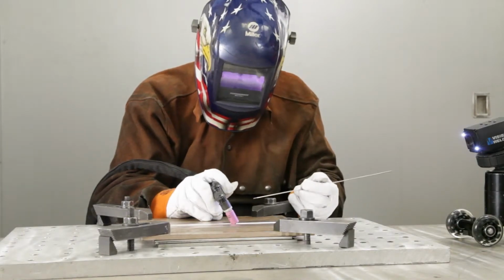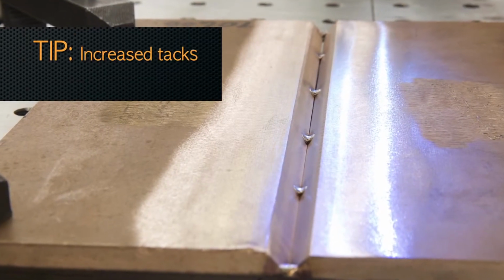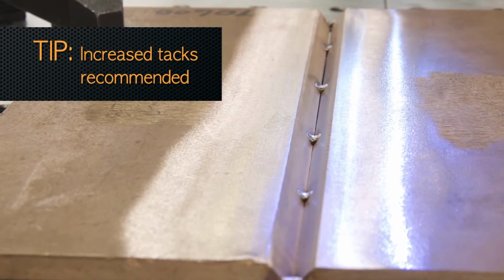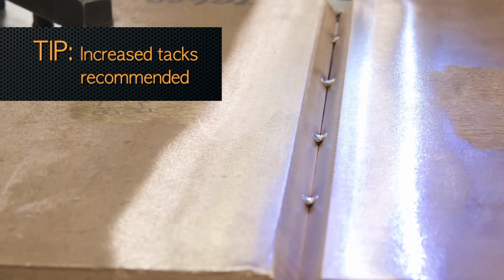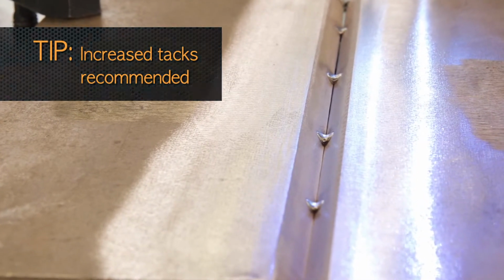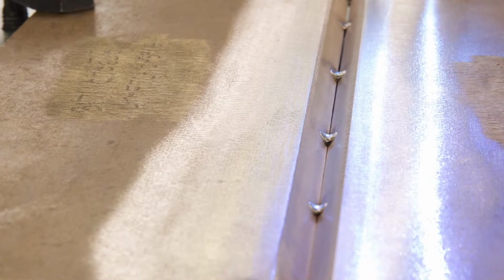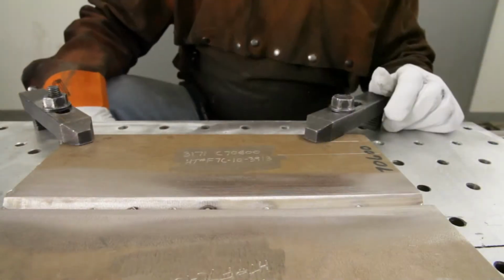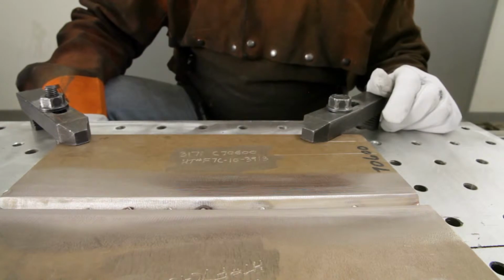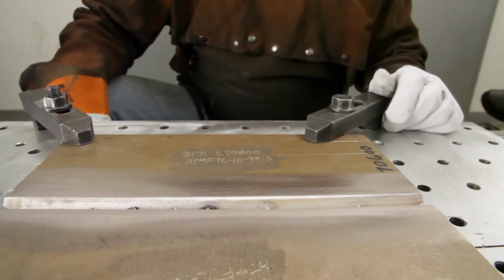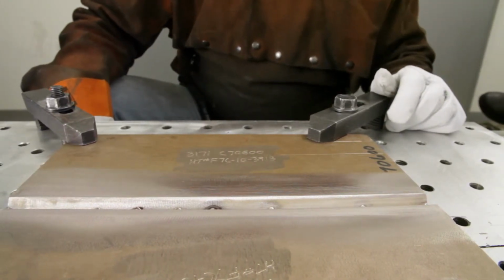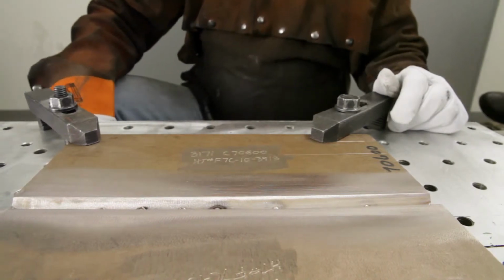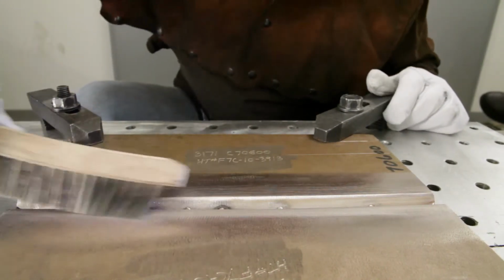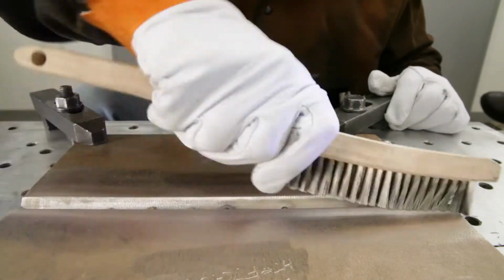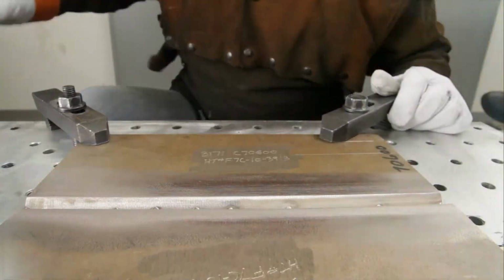It may be necessary with copper-nickel alloys to use more tacks than you would use for stainless steel or carbon steel due to expansion and contraction issues, and that's why we use a pretty narrow spacing between our tack welds. Once the tack welds are complete, the welder will wire brush to remove any oxides or smoke, again using a stainless steel brush that has not been used on anything but copper-nickel or stainless steel. And he'll inspect the tacks to make sure there's no porosity or cracks, and then we'll proceed with welding.